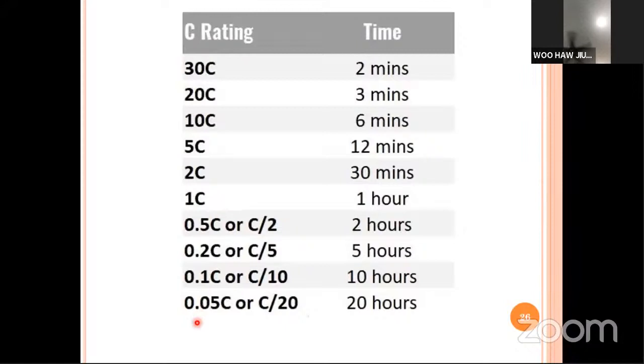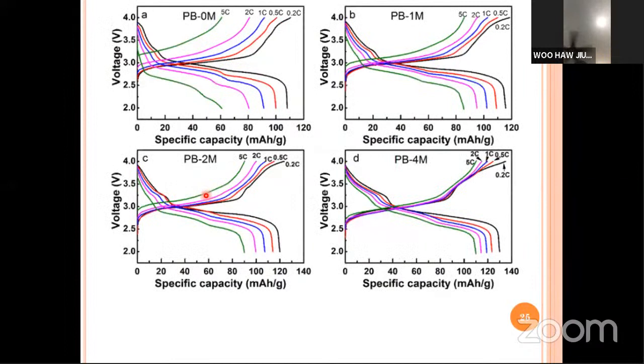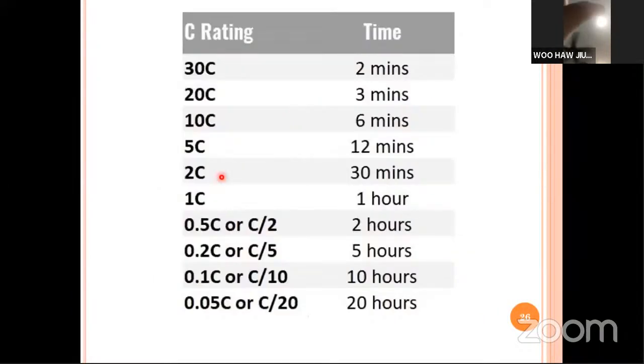So what they usually do, in order to show a very nice reading, is run and test their battery at 0.05 C, which takes about 20 hours of charging, in order to get a nice reading, for example, 150 milliampere hour per gram. But if you run at 1 C, like what we obtain here, we will be getting a very low specific capacity value. So what manufacturers show us is actually at 0.05 C. Now, if we run higher than 1 C, it actually takes a shorter time to charge. For example, at 5 C, it takes only 12 minutes to charge your battery. So obviously, we want a battery that can run at a higher C rating, right?